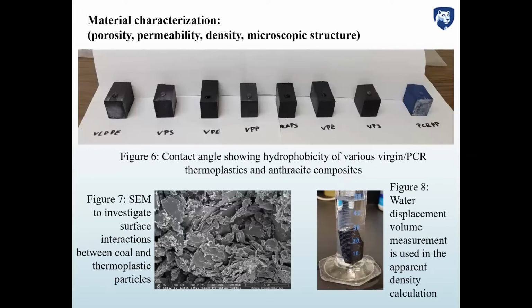So this just gives you an idea of some of the material characterization we're doing. We're doing porosity, permeability, density, and microscopic structures. You can see on the top, figure 6, the contact angle showing the hydrophobicity of various virgin and PCR thermoplastic and anthracite composites, which is a huge advantage when you consider that most of the degradation to cementitious materials and bricks are from water ingress and the freeze-thaw cycle, at least in this area.